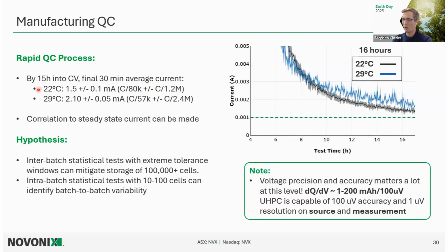So even looking at how early into this voltage hold process can we go? Here I've shown just up to about 16 hours or so where our kinetics between the two temperatures kind of cross over and start leveling out. And again, very, very consistently with a lot of confidence, we can say that these cells, maybe we can track this trajectory or make a correlation to that steady state current, especially in a manufacturing line where everything is so consistent every time, and have some kind of confidence interval and a tolerance to hit before just 16 hours or so. So within a day of a production cycle after formation, being able to use inter and intra-batch statistics to say that there is a problem with a certain set of cells to a really fine tolerance.